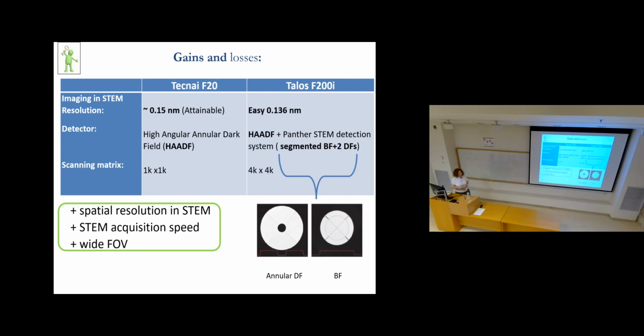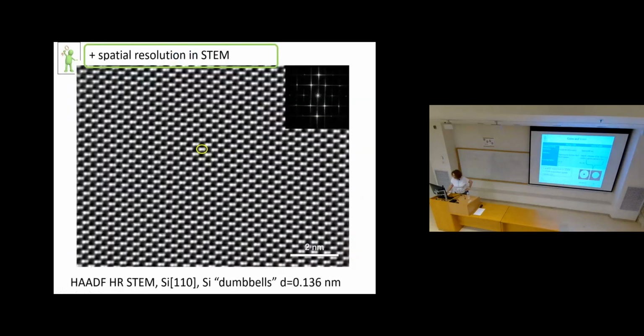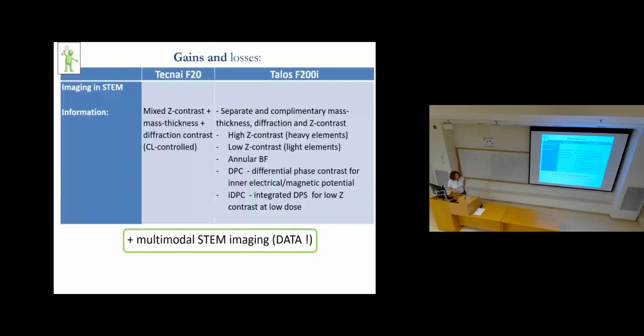of STEM detectors, the Panther STEM detection system, composed of the segmented bright field and dark field detectors on top of the HAADF. So we have much more sensitive and advanced HAADF, and in addition we have one bright field STEM detector and a few dark fields. So I mentioned two, but depending on the working distance, it could be more. Here I show the design of these segmented detectors. So the segments in the detectors are radial and quarters.